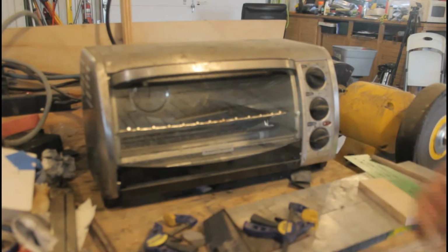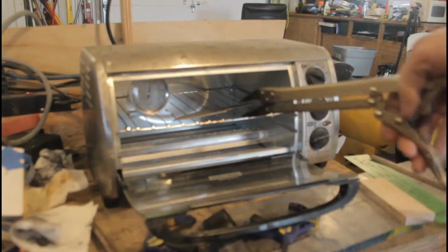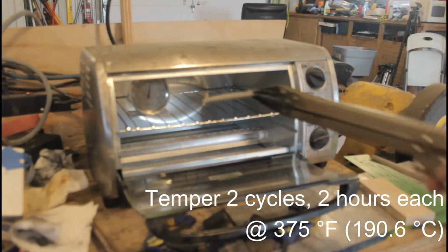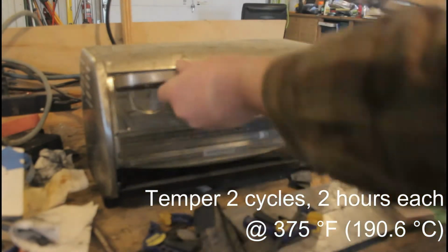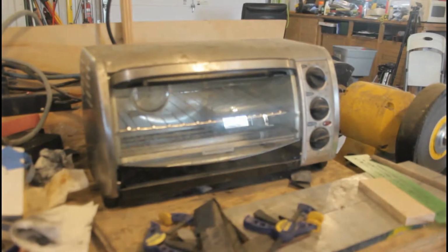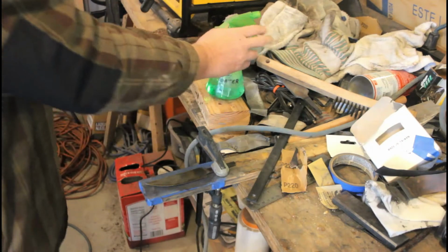According to my charts, I should temper this knife somewhere in the neighborhood of 375 degrees Fahrenheit for 2 cycles of 2 hours each. If all goes well, this should put my final edge hardness somewhere around Rockwell 60.